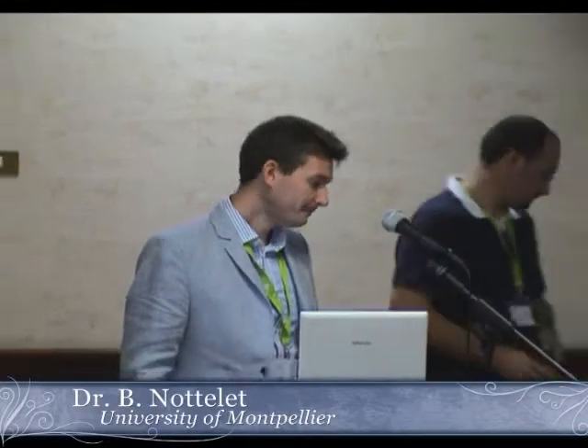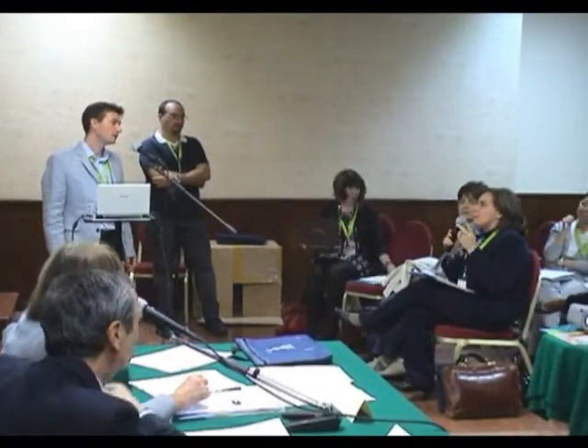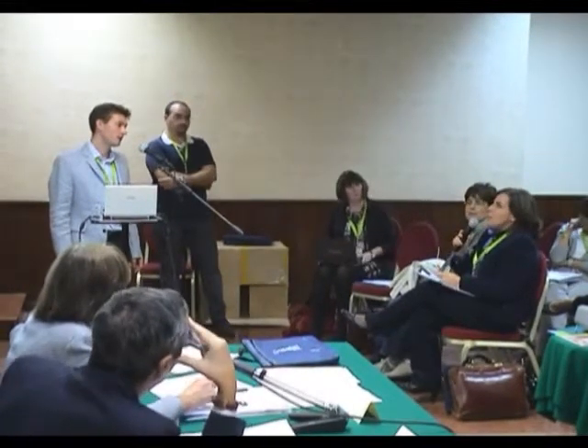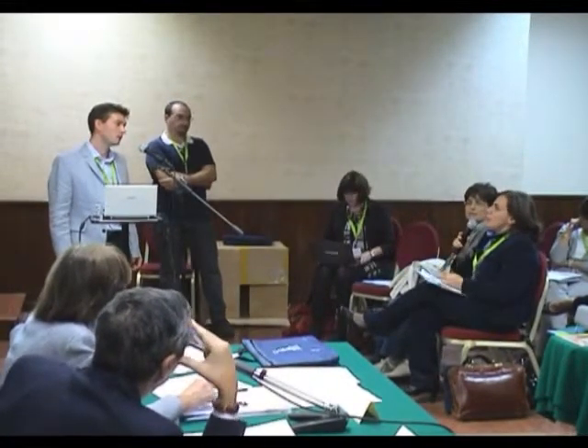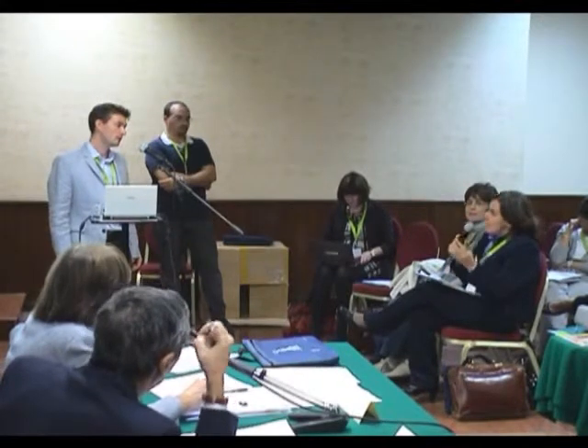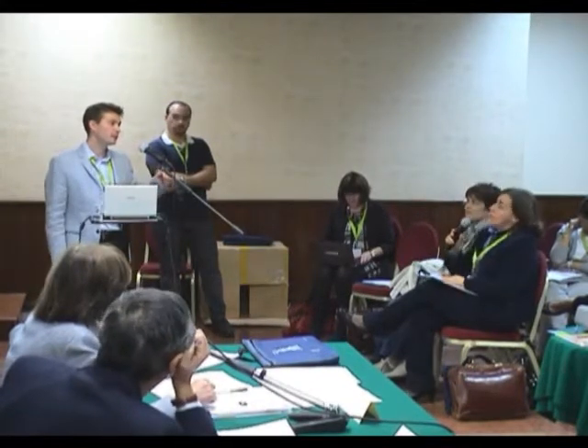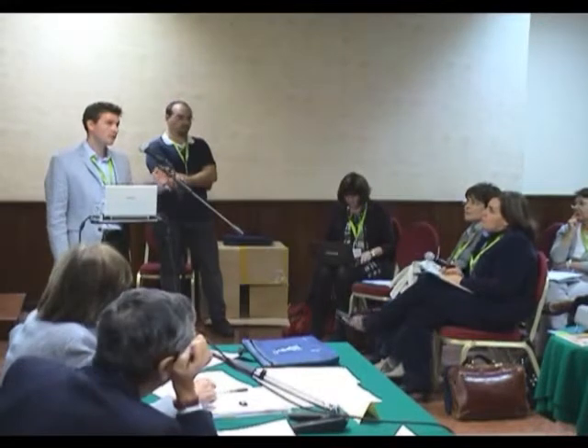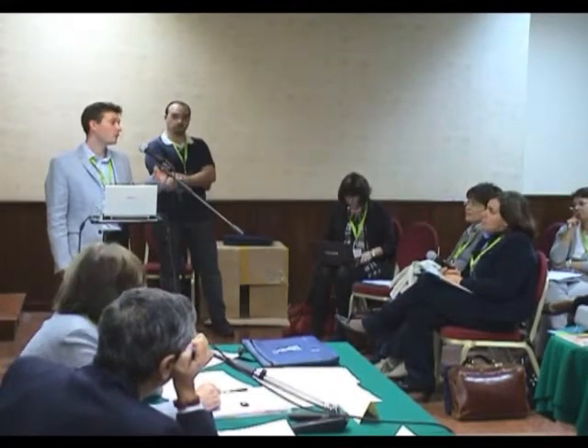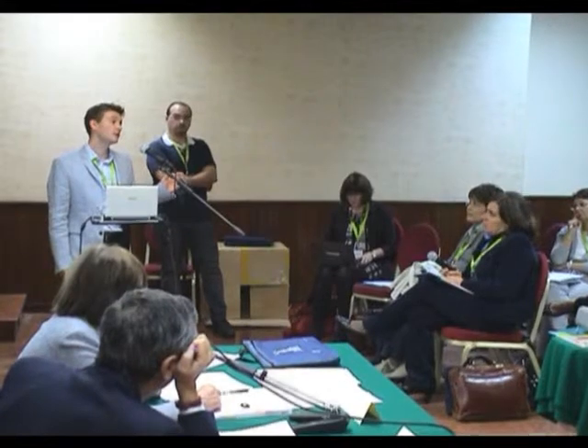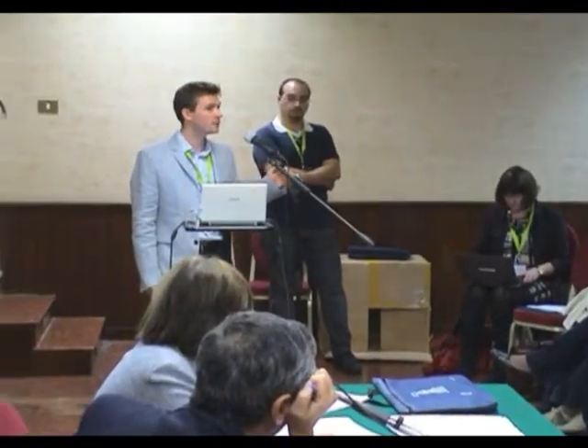Really, thanks for the fantastic presentation. In the case of a system with the modified surface, which kind of technique did you use to quantify the degree of derivatization of the system? On the surface itself? Yes. So what we used was only XPS. So we have an average composition of the surface, which corresponds to 10% of the surface covered by polyquaternary ammoniums. But it's not the real answer, and we don't have the density of grafting, for example, to date.